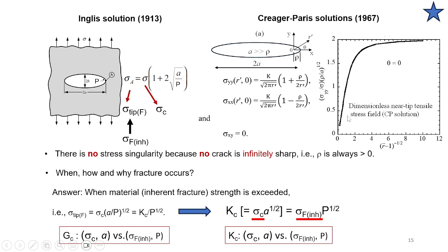I would probably skip most of it. This is why I said that in earlier days, we know this insight much better than Griffith was able to. So if you have spent enough time to look at this simple solution, you basically imagine I keep loading my sample until my tip reaches the strength. That's when breaking occurs. You'll find that this will be a relationship between the Kc and the strength of the material.